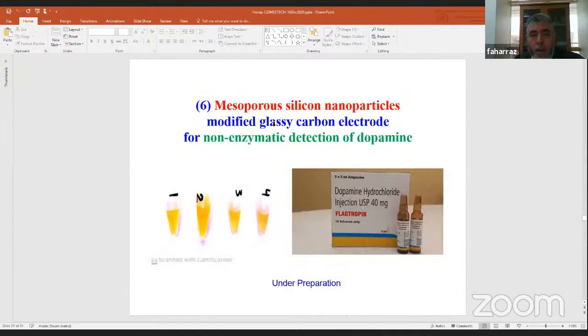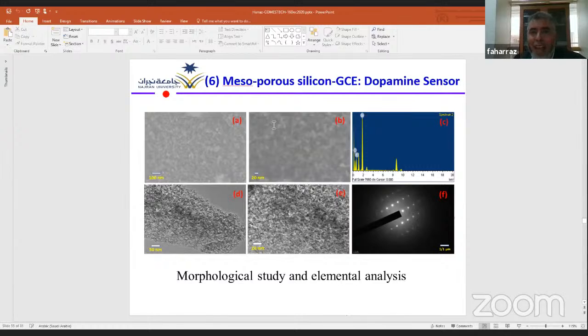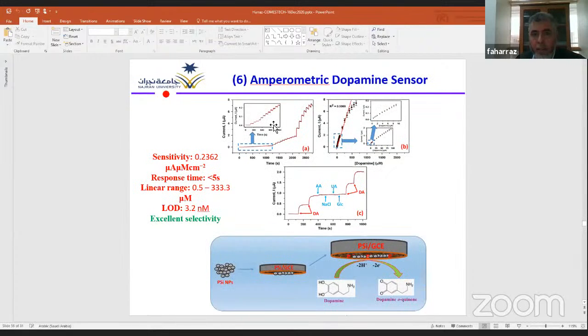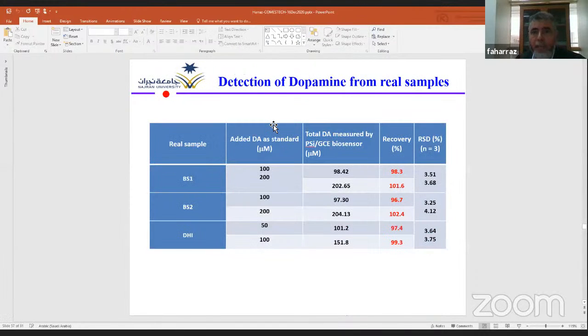The last example of the sensor part is the fabrication of mesoporous silicon nanoparticles modified glassy carbon electrode, and its utilization for non-enzymatic detection of dopamine. We detect dopamine in dopamine hydrochloride injection as well as human blood serum. This is just mesoporous silicon nanoparticles, nothing else. And we chemically modify the glassy carbon electrode, and this is our sensor device for dopamine. We also got an interesting result during the amperometric dopamine sensing. And this is the detection of dopamine from a real sample, with acceptable analytical results.